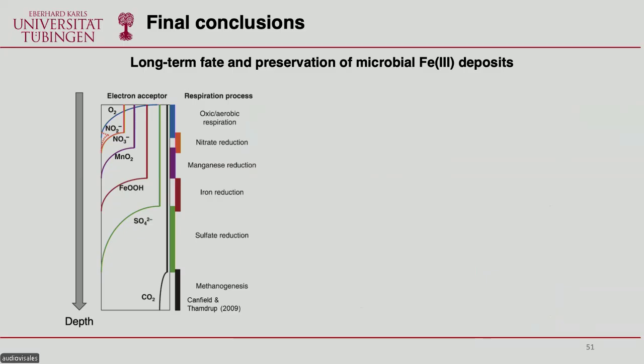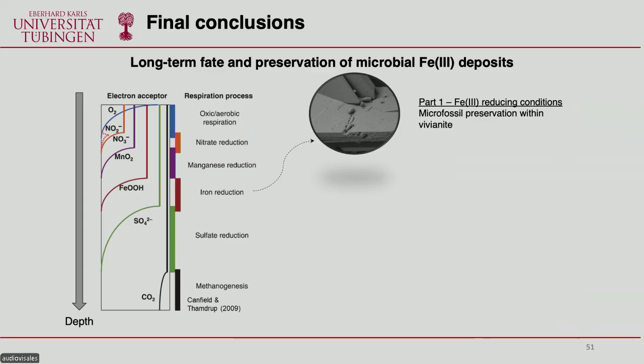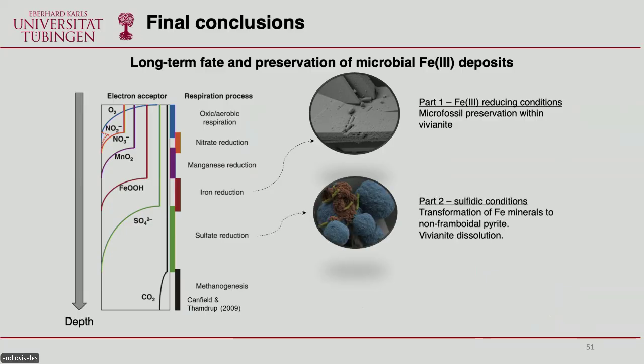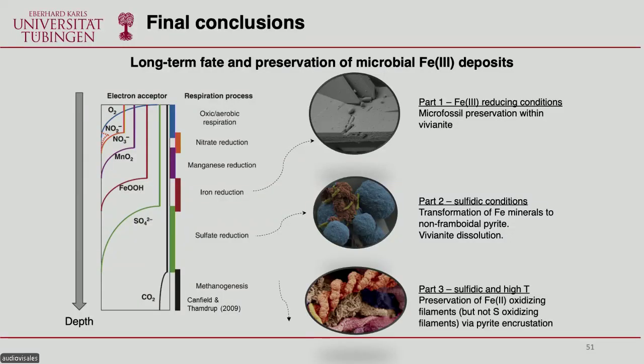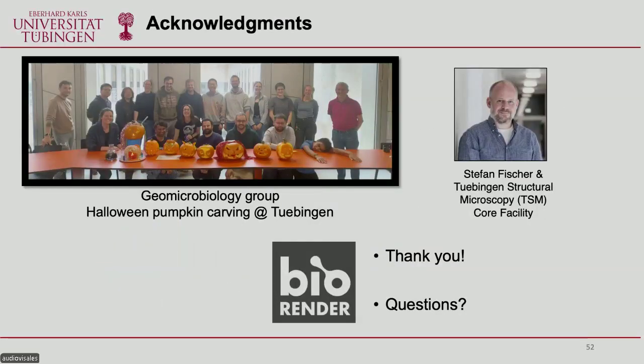Okay, and then just to summarize what we've learned from this talk: in part 1, we've seen that microfossils can be preserved within vivianite under iron-reducing conditions. Then under sulfidic conditions, we have transformation of the iron minerals to non-framboidal pyrite. At the same time, we saw that vivianite can be dissolved and the microfossils can be lost. And then in part 3, we saw that the iron oxidizing filaments can be preserved well, but not necessarily the sulfur oxidizing filaments, and this is related to pyrite encrustation. Of course, this has implications for how we look for biosignatures in different environments. And with that, I will end my talk.